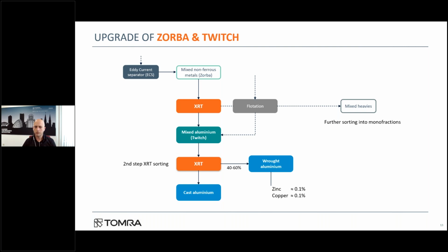So the goal here is to really concentrate the wrought alloys and produce a premium quality aluminum, where after melting, levels of copper and zinc of around 0.1% can be reached. So there is a significant added value for this fraction, and it allows recyclers to have additional channels to sell directly to the smelters, also the ones that require higher qualities compared to the Twitch material.